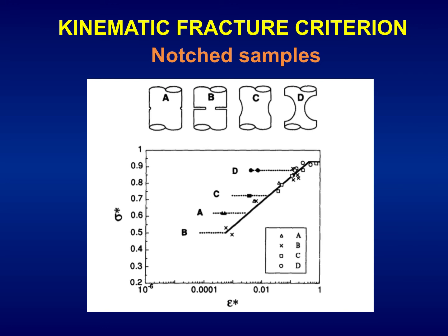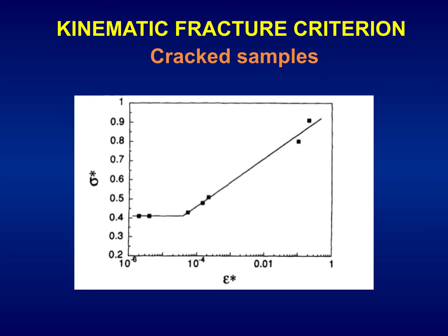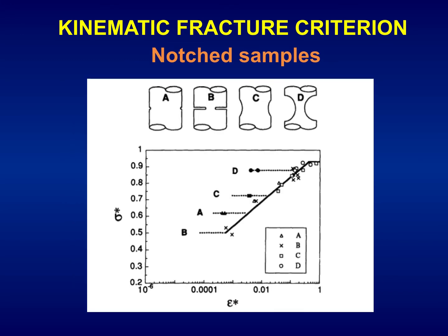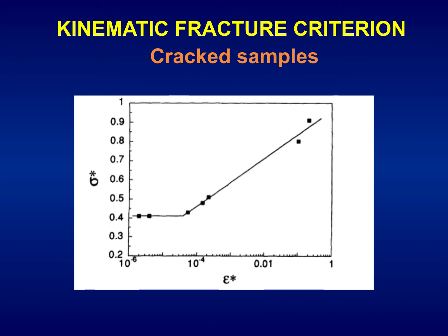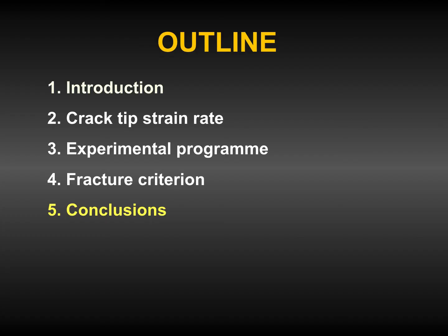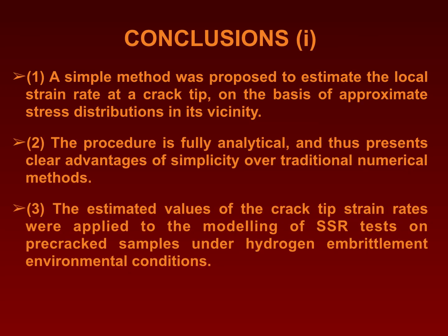Going back to the results from pre-cracked samples, we have a similar curve, and the two universal curves approach each other, thus demonstrating the validity of the present approach of a kinematic fracture criterion for pre-cracked samples on the basis of the crack tip strain rate. Let's go to the conclusions.